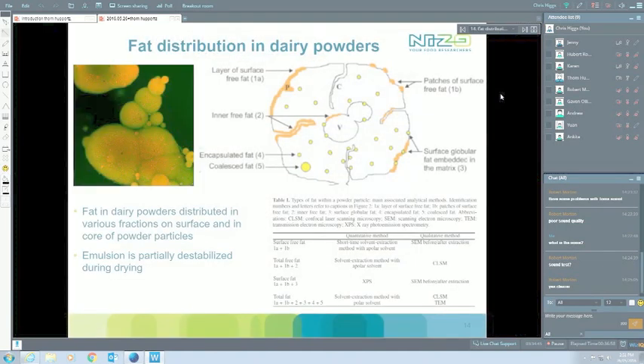Of course, one of the key things in these powders where the atomization has a big effect is what happens to the fat in dairy powders, in whole milk powders in general, because what we typically see, if we put whole milk powder under a confocal microscope, we see protein in green, we see fat in red in a picture like that, and what we essentially see there is a lot more fat on the surface than we would like to see. And almost no matter what you do, you get quite a bit of fat on the surface, but we need to control that as well, because it will have effects on flavor, stability, and functionality. How can you dissolve your powder, because anything with fat on it is going to be a lot more difficult to dissolve.